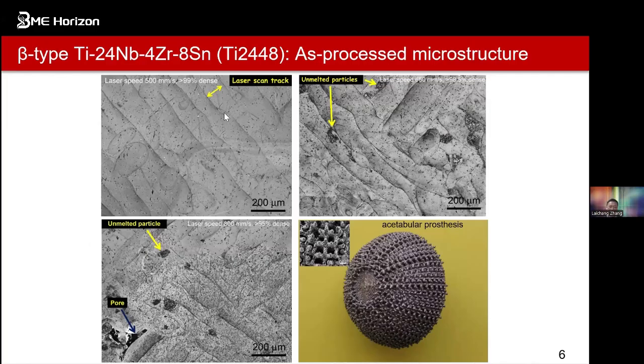So that's for the nearly fully dense sample at 500 millimeters per second, and the wide one is intermediate density at 650 millimeters per second, and with a lower density, at 800 millimeters per second. When you see a really fully dense sample, you can only see the laser track. This is created during the selective laser melting processing.